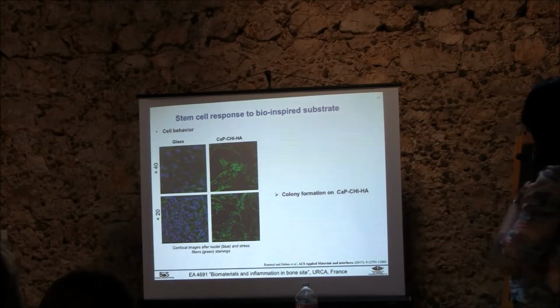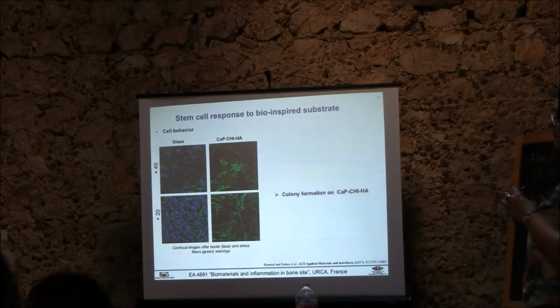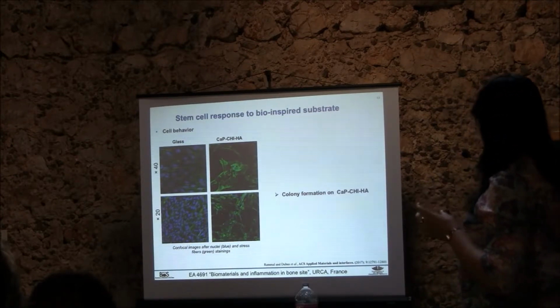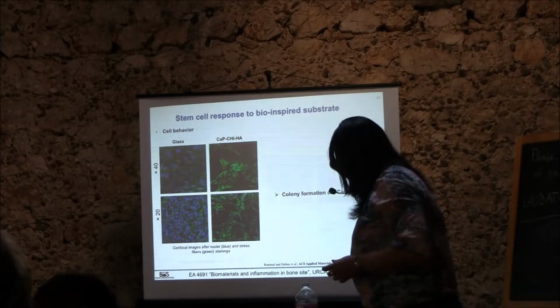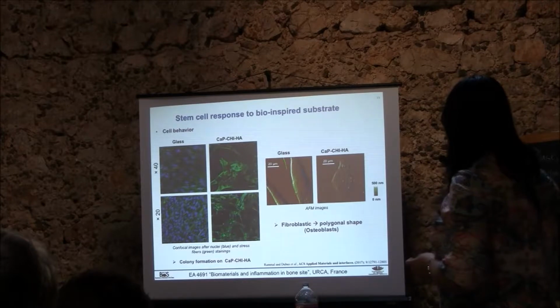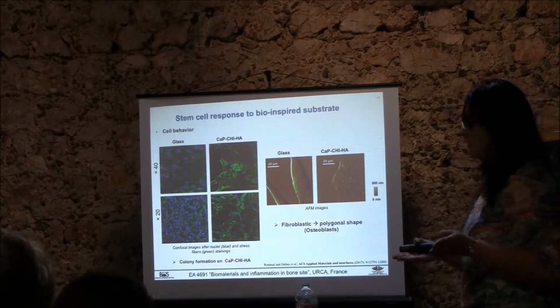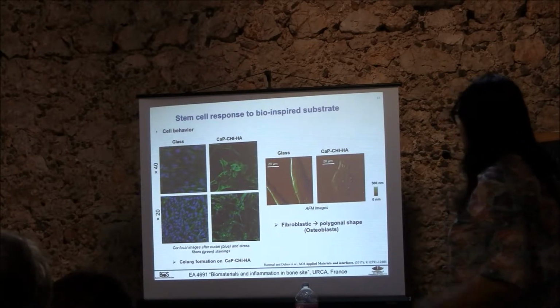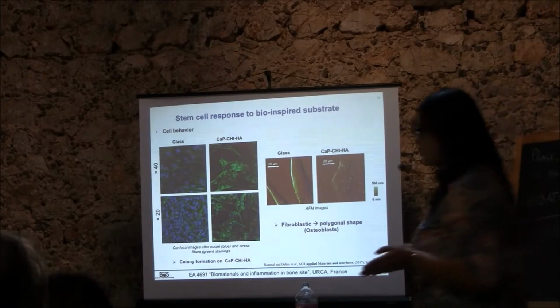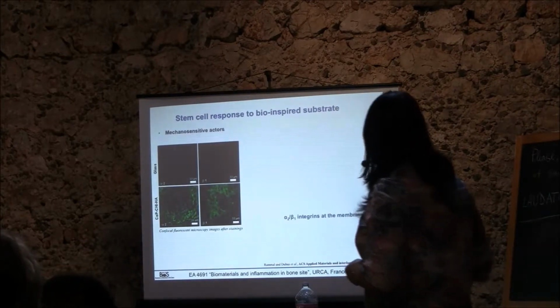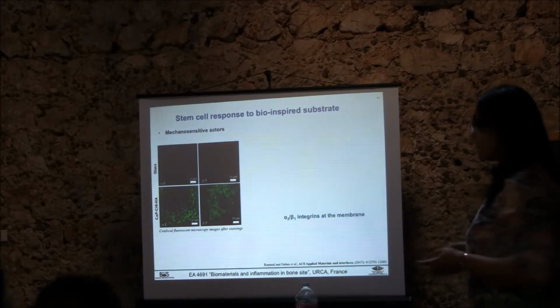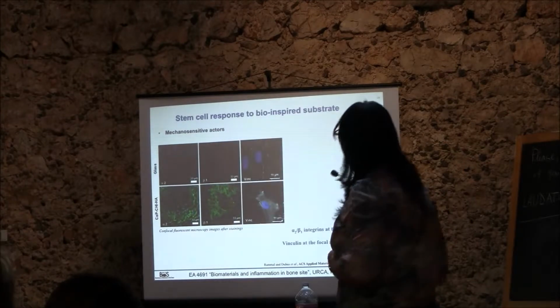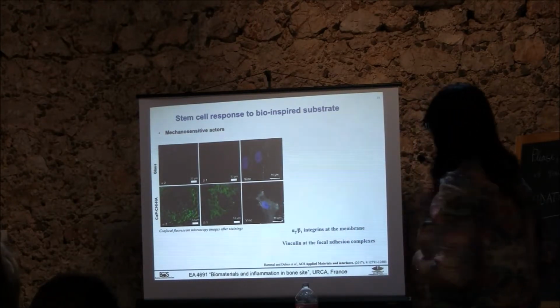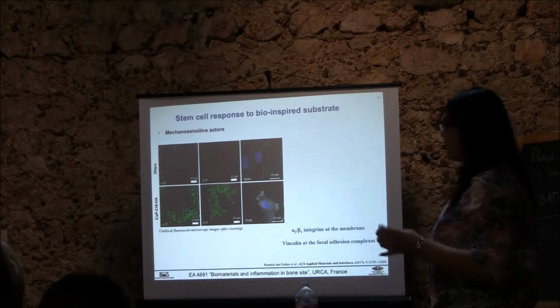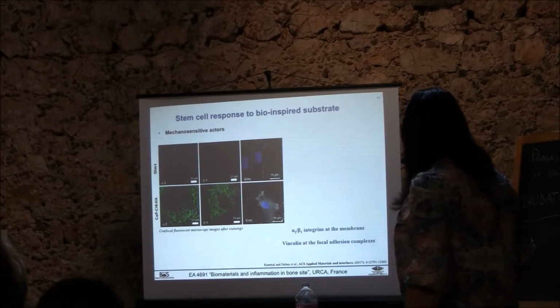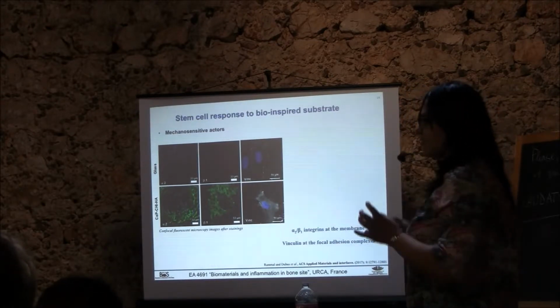After a week, on our calcium phosphate, cells behave differently than on glass and form small colonies. In these colonies, cells switch morphology from fibroblastic, which is known for stem cells, to polygonal morphology, which is more characteristic of osteoblasts. These cells express integrins, which are mechanosensitive molecules, recruit vinculin at the edge of cells, and maintain it at this position because cells are under traction. In contrast, on the glass, we observe vinculin around the nuclei.